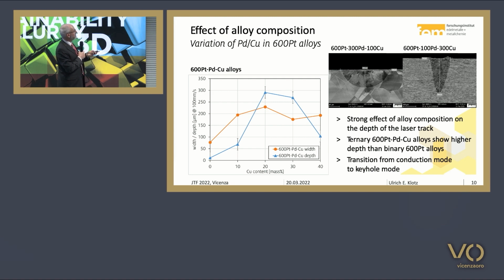If the copper and palladium ratio is exchanged, here we have 300 palladium, 100 copper, and here 100 palladium and 300 copper. The copper-rich alloy shows a much deeper laser track. This is a typical example of the keyhole mode, and the scale is even higher, so this laser track is really much deeper.